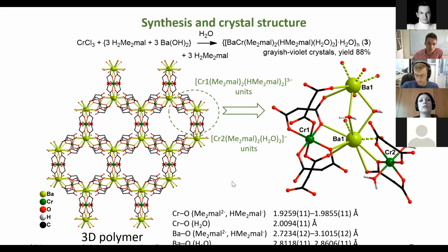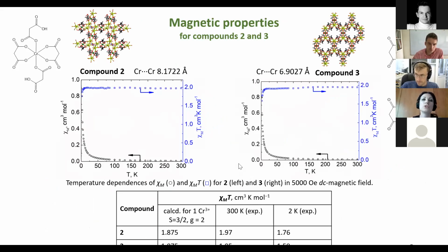Barium atoms are linked in pairs by bridging water molecules. The temperature dependencies of χT for compounds 2 and 3, which contain mononuclear chromium units, are similar in shape. At 300 kelvins, χT values are in good agreement with the theoretical value for one isolated chromium ion.